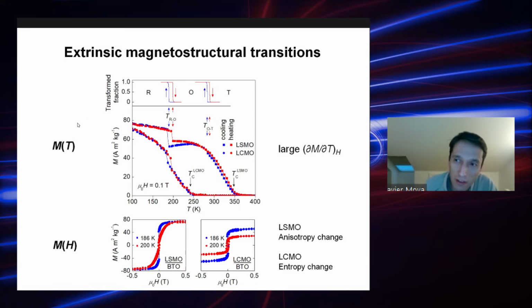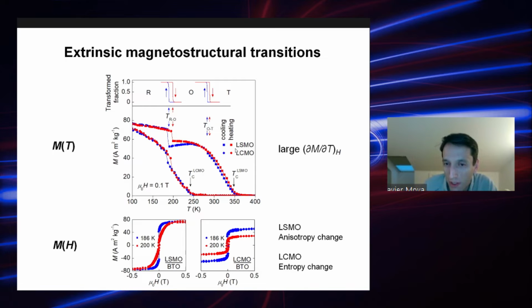So if you measure magnetization as a function of temperature of this film, in this case LSMO, which is shown here with the square data, and you also look at another compound, which is LCMO. So this will be the calcium manganite, which has a stronger magnetostructural coupling. You can see that around 200 Kelvin, where the transition in the substrate between orthorhombic and rhombohedral phase happens, there are big jumps in the magnetization, which is a signature of this extrinsic magnetostructural transition. We are changing at the same time structure and magnetic ordering.